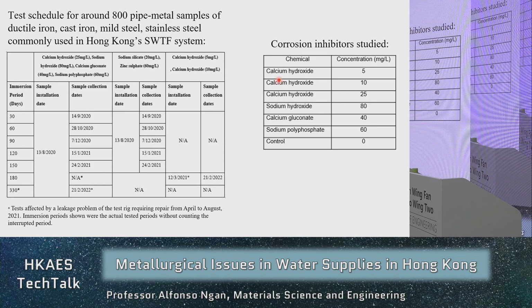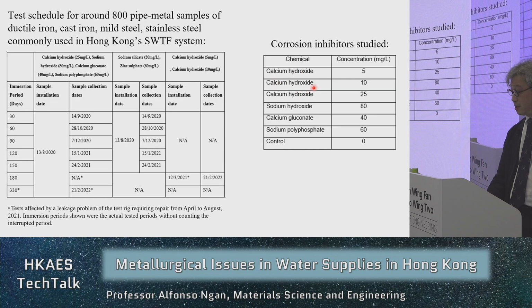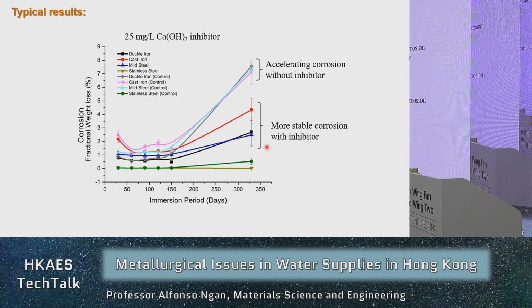And then we added different chemical inhibitors, say calcium hydroxide, lime basically, at different concentrations, ranging from 5 to 25 milligrams per liter, as well as sodium hydroxide, calcium gluconate, sodium polyphosphate, and of course the control without any chemical inhibitor added. So that's just the pure seawater. So those are the typical results. Of course, we generated lots of results for different conditions. This is just to show a typical set of results for 25 milligrams per liter of calcium hydroxide for different materials, as well as the control, which is without the inhibitor.